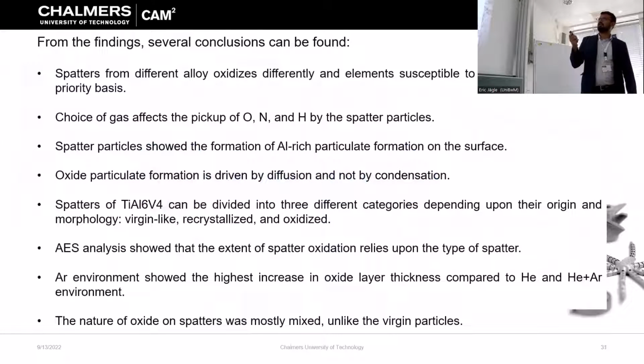Okay, so that was all. I will conclude my presentation on spatters. Spatters from different alloys oxidize differently, and the element susceptible to oxidation has the priority when it comes to oxidation. The choice of gas affects the oxygen, nitrogen, and hydrogen pickup. Spatter particles show the formation of aluminum-rich particulates on the spatter surface. And oxide particulate formation is driven by diffusion and not so much by condensation.